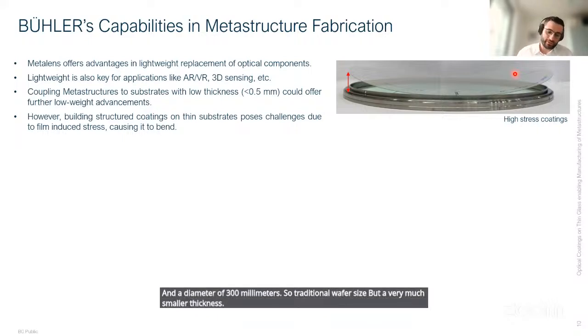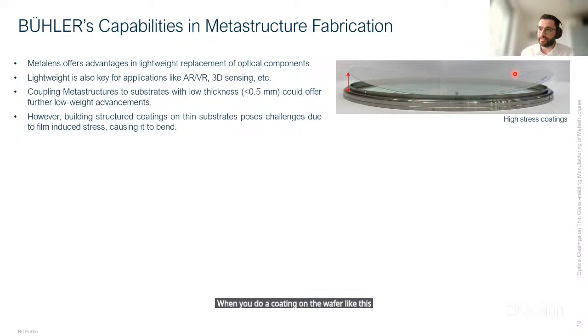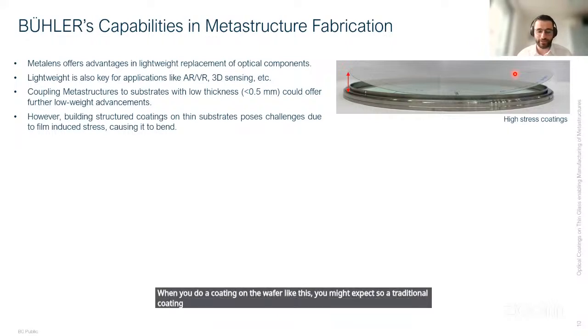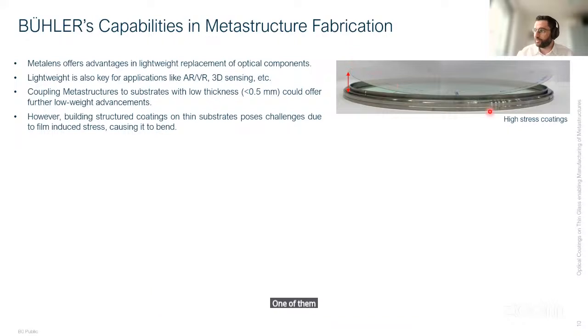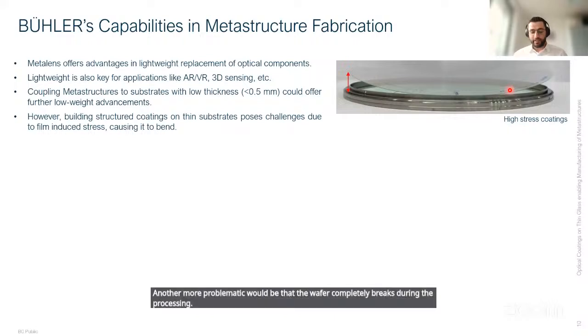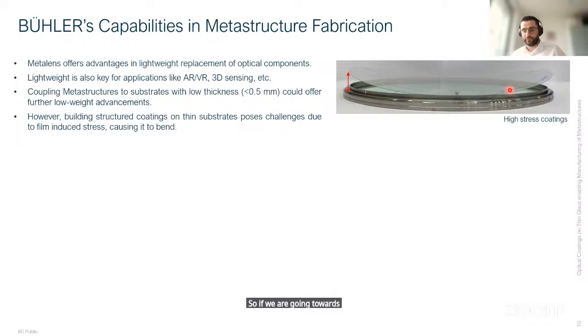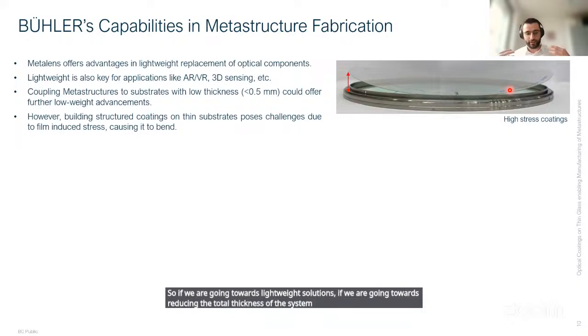When you do a coating on a wafer like this, a traditional coating might end up in two different results. One of them is, you see what is happening here, the wafer bends a lot. Another, more problematic, would be that the wafer completely breaks during the processing. So if we are going towards lightweight solutions, if we are going towards reducing the total thickness of the system, we also need to think from a manufacturing point of view how we can reduce the stress induced on glass substrates with a certain thickness and a certain diameter. And this is what we are working on.